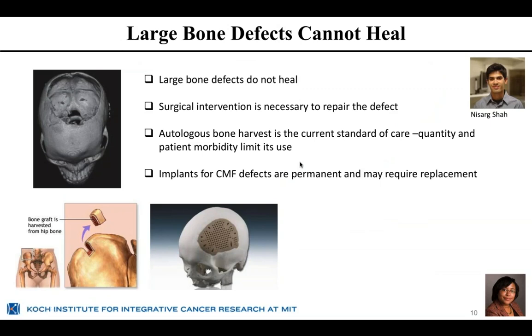We can actually use this to address a number of different issues, such as large bone defects that are so large that they cannot heal. For example, in this work, which was done by my former graduate student, Nisarg Shah, he actually looked at the coating of membranes, which allowed us to essentially cover these large cranial defects and regenerate bone.